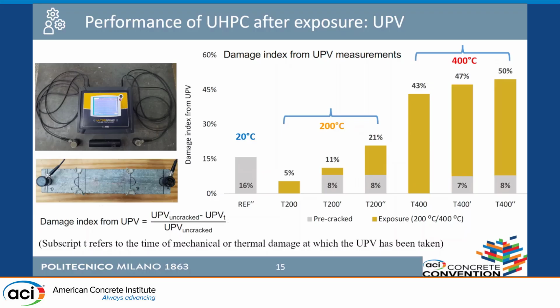This means that the damage induced by pre-cracking is even more than the damage induced by heating. If we pre-crack and we heat, we have a loss between 11 and 21%. So in the end, a good estimation is the sum of these two contributions. Then the same for 400 degrees C, but obviously in this case we have a far larger damage, and so the difference between uncracked and pre-cracked sample is less evident.